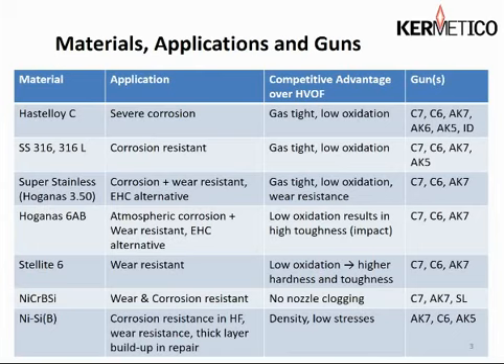6AB is a Hoganas product. It's a ferritic stainless, RC60-ish, very wear resistant, and a good alternative to electrolytic hard chrome. Applied coatings have low oxidation in the coating structure, and they are surprisingly tough as hard coatings go. And once again, this is limited to our larger guns, only because we've had no reason to spray it with our smaller guns.